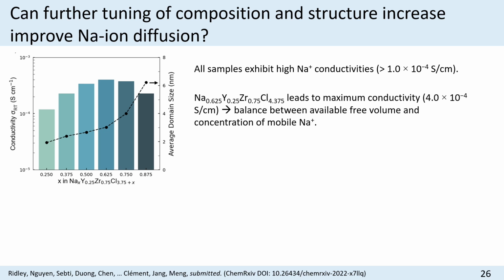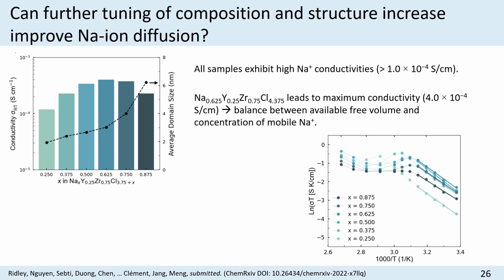So on the order of 4 × 10⁻⁴ Siemens per centimeter for the better ones. So for this 0.625 composition, we're now getting to a point where these materials are starting to get to be good solid electrolytes for sodium-ion batteries. The problem is, if you now plot the log of the conductivity versus the inverse temperature, you would expect an Arrhenius behavior if they behave as expected.